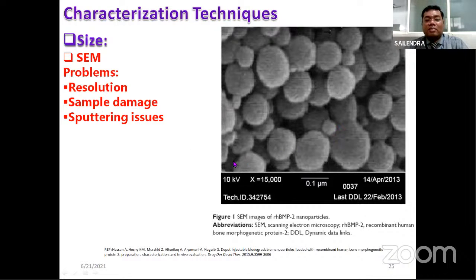Now, in scanning electron microscope, as you increase the resolution, there is a high chance that you are going to damage the sample, because these nanoparticles are not going to handle that much amount of energy being thrown at them. Before you can take any image, even your sample can get destroyed. So resolution is a major demerit of this scanning electron microscope. You get your sample damaged. And sputtering, what is the sputtering issue?